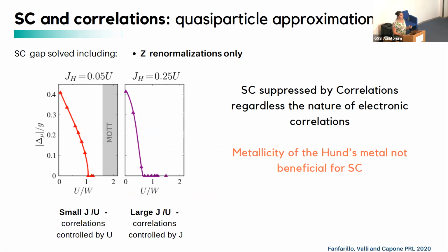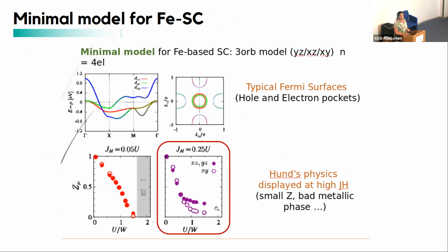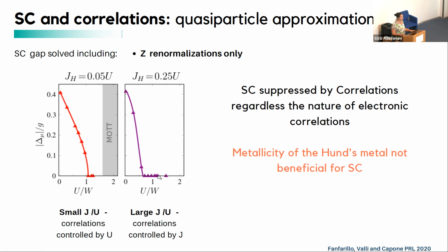I'm computing the gap with the BCS equation. I'm renormalizing the gap, using the superconducting coupling here, with some renormalization factor, and I show you the result for low J and large J, using only the Z renormalization factor here. You see there is something that may be unexpected. The gap for the Hund's metal is dying exactly as the gap for the low J value. So essentially, superconductivity is suppressed by correlation regardless of the nature of the correlation. And the fact that you still have a residual Z factor here, so the system is still a bit metallic, is not appreciable, at least at this level of calculation.